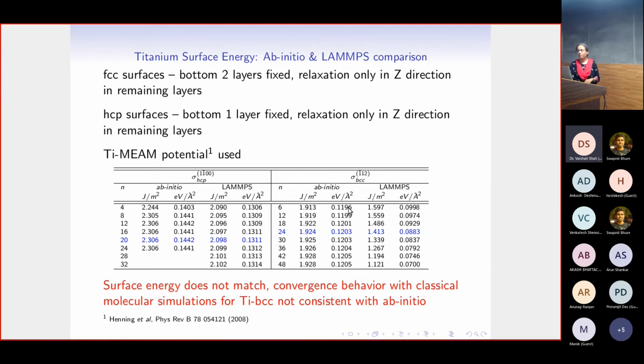Similarly, for BCC, the energy starts at some number, then increases and more or less stabilizes around some number. But if we look at the surface energy profile from the LAMMPS simulation, we see a completely different behavior. It starts with a higher number and goes towards a lower number. That's also okay, but we are not able to see that it converges at that number.